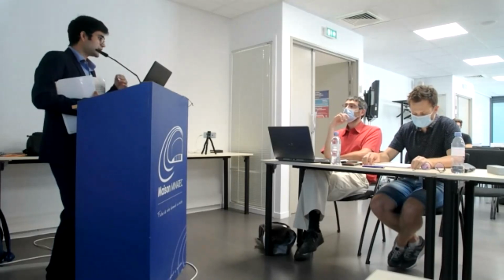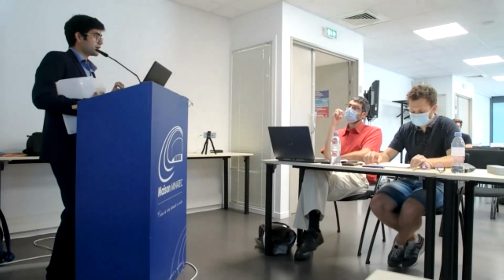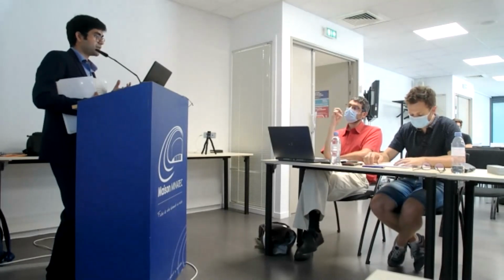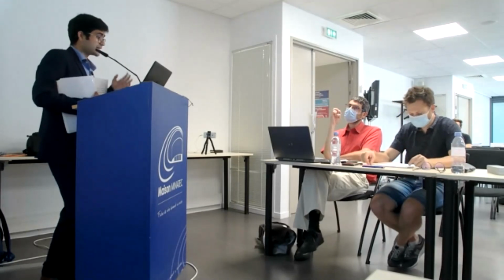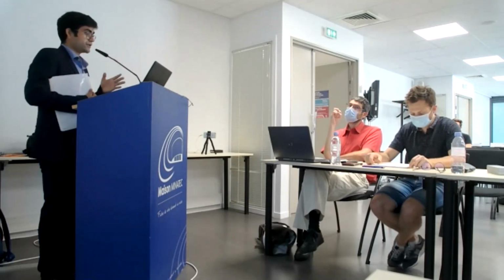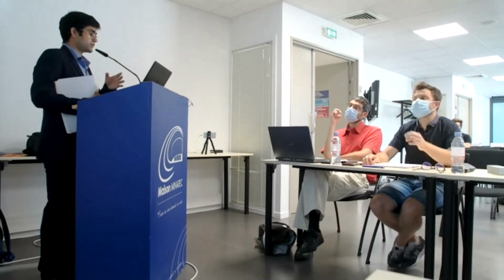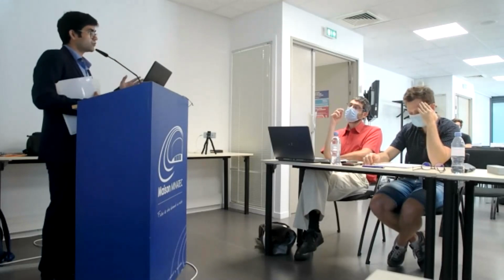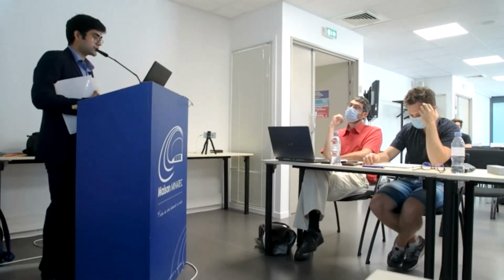For example, we have shown that the coalescence solid fraction is very sensitive to cracking. And if we are able to control this coalescence solid fraction, basically controlling this metallurgical parameter of the alloy, we can have better crack resistant microstructures. And this can be true not only for 6061. If we are able to control this metallurgical parameter, it can be true for other crack sensitive alloys. So this is a way in which I would prioritize. The first is going into controlling alloy development parameters.